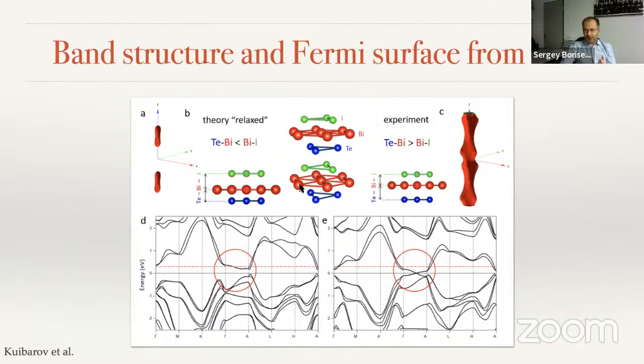And this small difference results in a very pronounced difference of the band structure. Thus, the full characteristic of the material is completely different. In this case, we have a semiconductor with a finite energy gap. In this case, we have a very unique 3D semimetal, in the sense that this 3D Dirac point, we also call it a minimal 3D Dirac semimetal, because there is only one Dirac point, 2 per Brillouin zone, and it's very well isolated from everything close to it. It's isolated in terms of momentum, and it's isolated in terms of energy, resulting in what we call a Dirac band of the order of 0.4 eV. This would be a very interesting material for applications if this is the case.